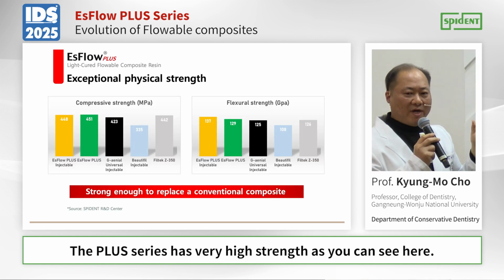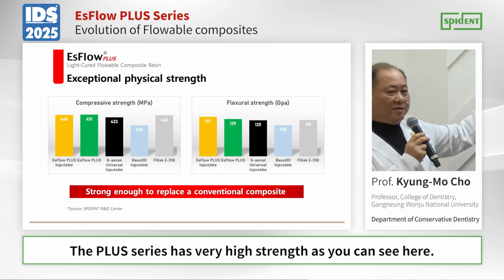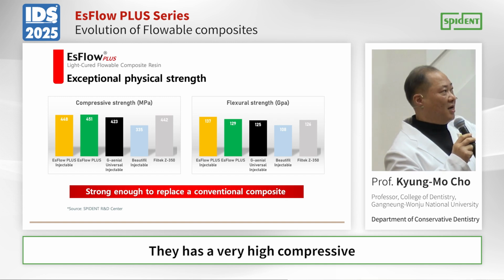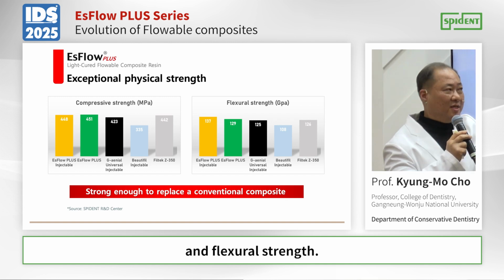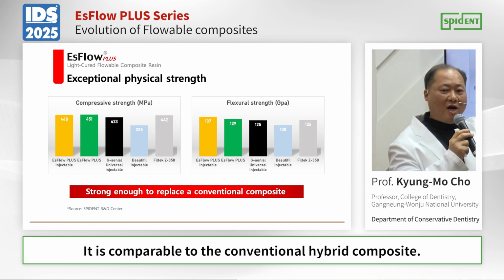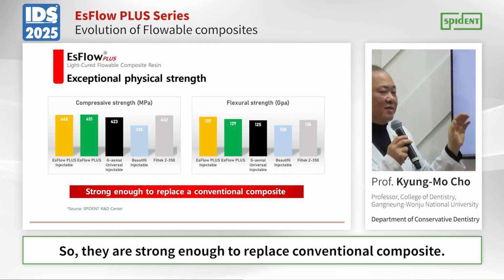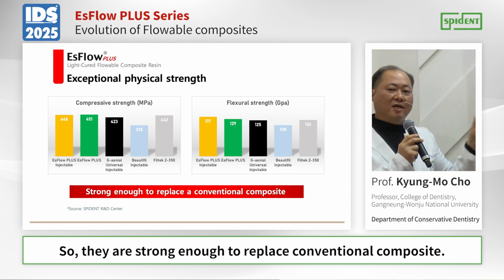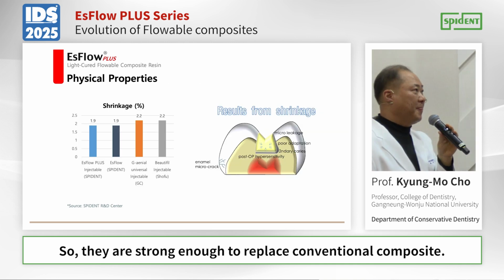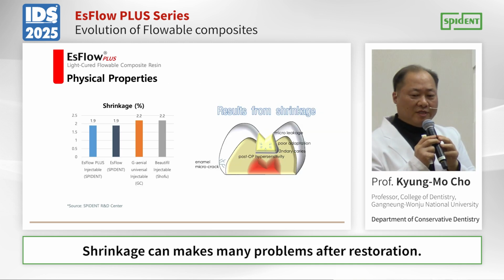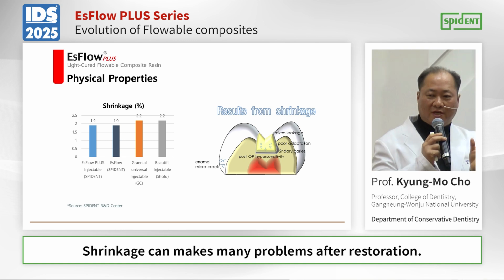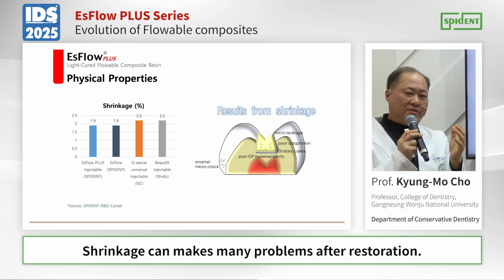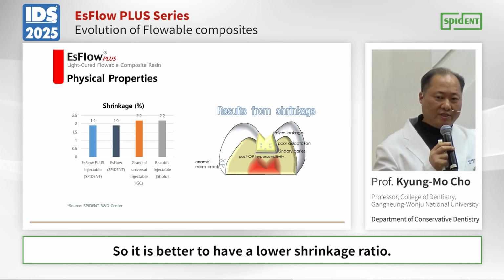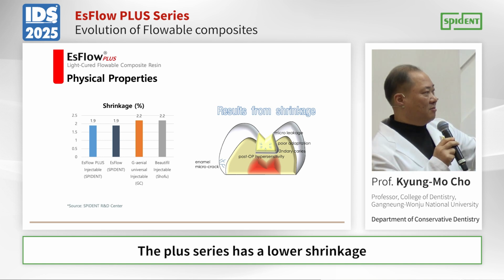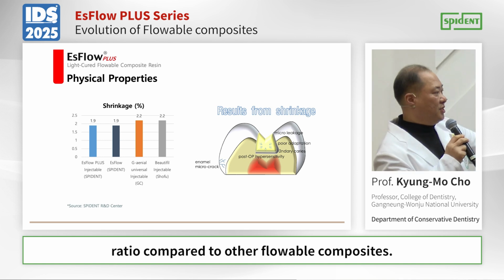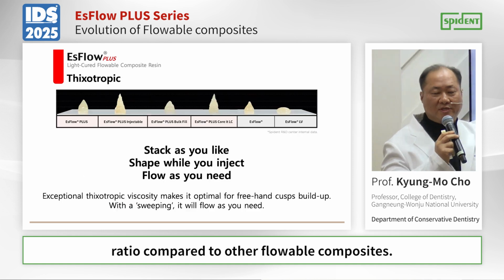The Plus series has very high strength. As you can see here, it has very high compressive and flexural strength. It is comparable to the conventional hybrid composite, so it is strong enough to replace conventional composite. Shrinkage can cause many problems after restoration, so it is better to have a lower shrinkage ratio. The Plus series has a lower shrinkage ratio compared to other flowable composites.